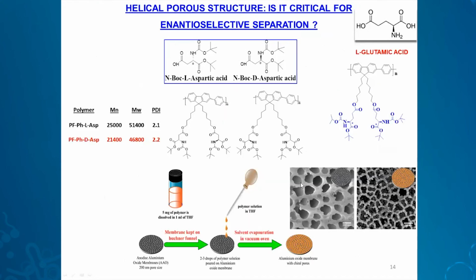So moving on, we wondered whether this property was due to that specific morphology of the polymer. I showed you the SEM image, which is the porous fibrous morphology. So whether that was the reason for that. For that, we designed two more polymers shown here, polyfluorene again. But this time, instead of the glutamic acid in the previous example, we used aspartic acid. We made both the L and the D protected aspartic acid appended polyfluorenes, and their molecular weights are also shown here. When we checked the morphology, we realized that they did not show the porous structure, and in the powder form, their separation efficiency was very poor. Although it showed some enantiomeric separation, the efficiency was very poor.